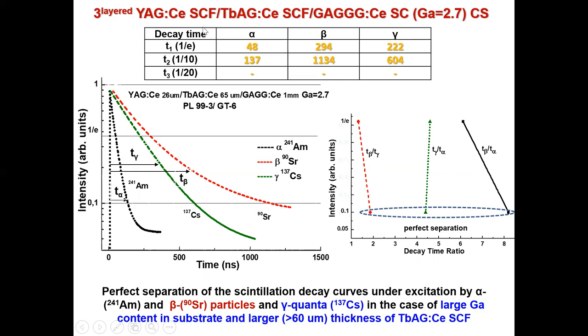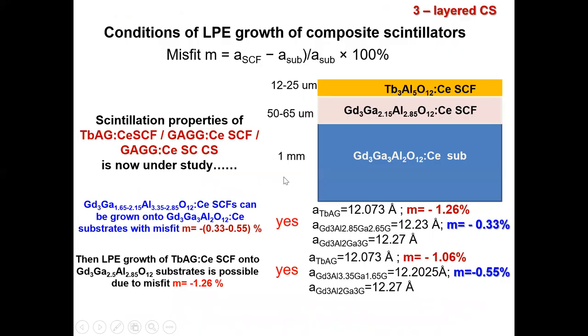At the moment, this is the best type of three-layered composite scintillator for simultaneous registration of different kinds of ionizing radiation including alpha particles, beta particles, and gamma quanta. We are also now considering another type of combination based on TbAG garnet and GAGG-based films with gallium content lower than the substrate gallium content of 3. We have performed LPE growth of such composite scintillators and are now investigating their scintillator properties. Results will probably be presented at the next international conference.